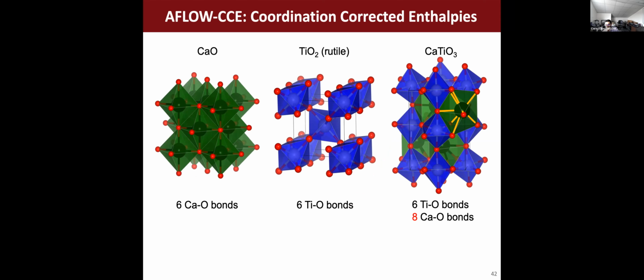Another question: what is the typical error value of a DFT enthalpy calculation of an ionic compound? Great question. I was going to show that in a few slides, but for the oxides, it can be as large as 200 meV per atom. So you can imagine that if the point on the convex hull has an error bar of 200 meV per atom, we have no sense of reliability of any analysis that's done on the convex hull. These errors are very large, and it's very important that we correct them.